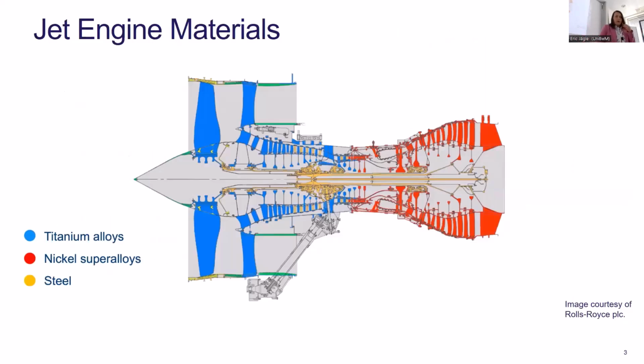And if we look at a quick cross-section of the jet engine and where the different materials are being used, this is about 20 years old, and you'll see at the front of the engine, we have quite a lot of titanium. It's nice and light, we like it, but it doesn't have the temperature capability. So as we move through the engine to the higher temperatures, we increase the amount of nickel that we use. So the new engines, the new concepts of engines that we're looking at now, have that nickel-based superalloy red section coming further and further front, right, as the temperatures are increasing.